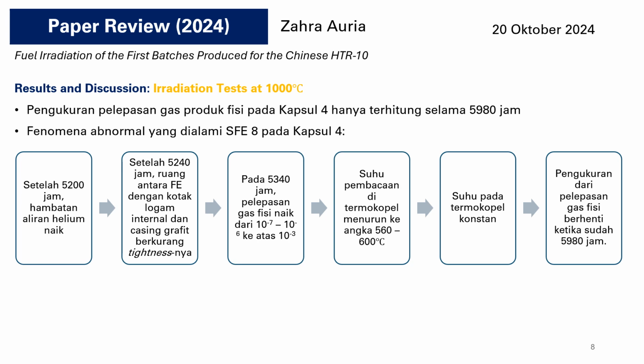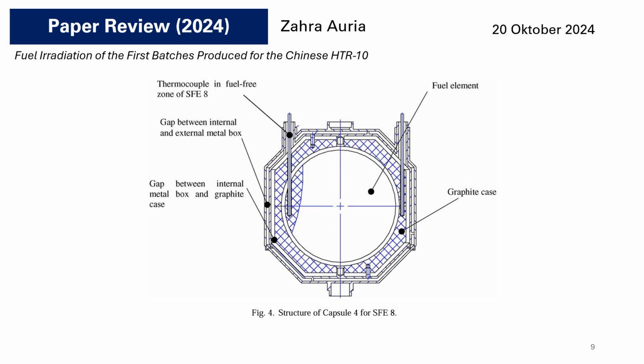The temperature reading of the thermocouple plummeted to 560 to 600 degrees Celsius, and after that the temperature of the thermocouple was constant, and the measurement of the gaseous fission product release was stopped when it reached 5,980 hours. So this is the structure of capsule 4 in which the abnormal phenomenon happened.